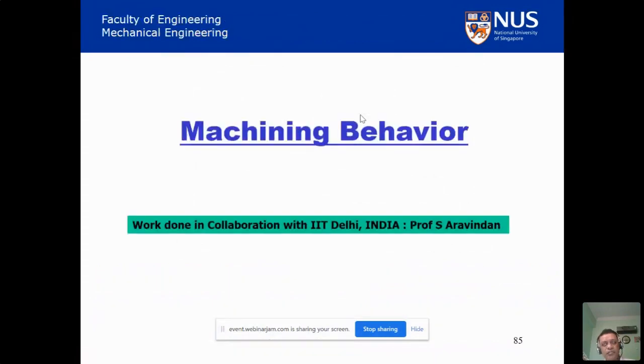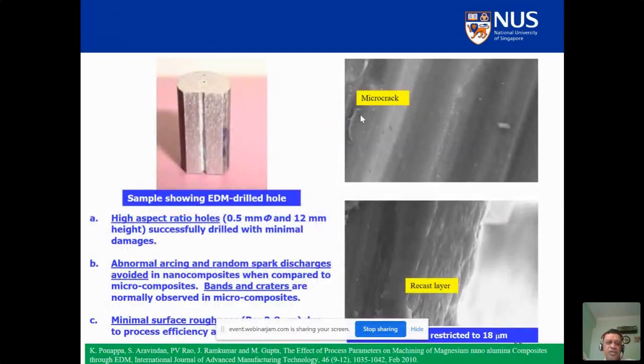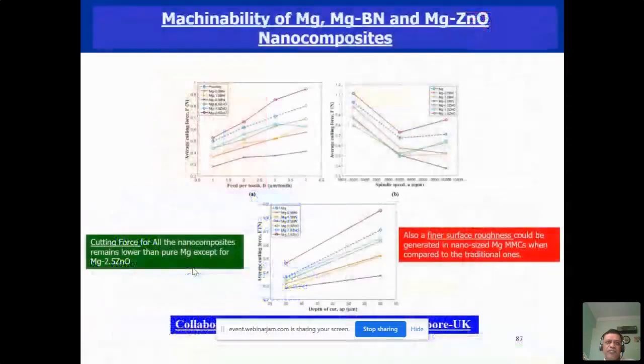Now, if you have a material, you have to machine it also to put in a system, and some of the machining work we did in collaboration with IIT Delhi quite some time back with Professor Aravindan there. And he wanted to investigate the possibility of machining deep aspect ratio holes, as you can see in the top image here. And his observation was that we can drill high aspect ratio holes, no abnormal arcing, and acceptable surface finish.